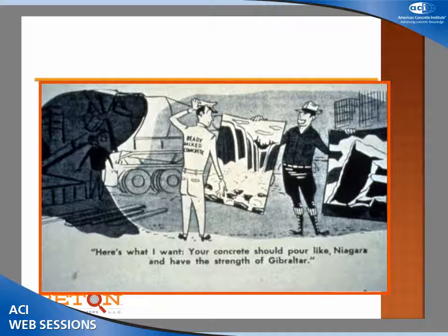This was not really possible, right? You could make pour like Niagara concrete. It wouldn't have the strength of Gibraltar. It might have the cracks of Gibraltar. Similarly, if you wanted high strength, you got those sticks out that the Roman guys had and you pounded the concrete in place. We've gone away from that, and that leads us to a problem as well, because once upon a time, for a given set of concrete mixture proportions, if you added additional water, the slump went up.